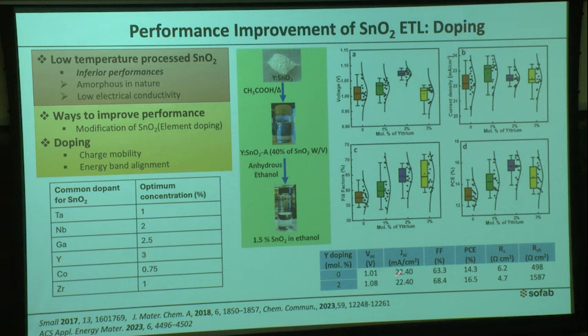The improvement in power conversion efficiency is coming from improvement in VOC and fill factor. Comparing it with undoped tin oxide, which is pure tin oxide without yttrium, we were able to get 14.3% efficiency. But when we incorporate 2 mole percent of yttrium, we get 16.5%. That is a huge improvement, about 2%.